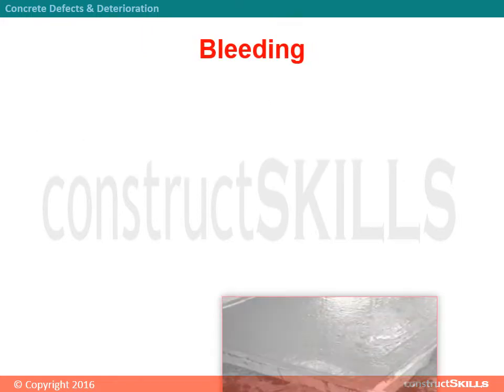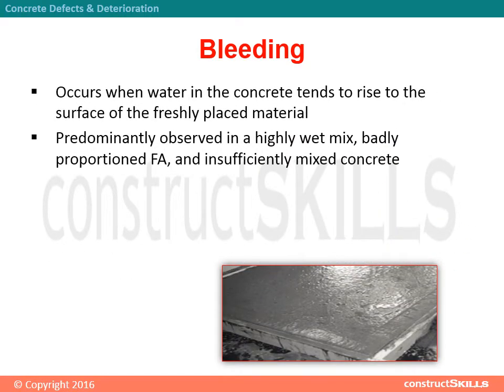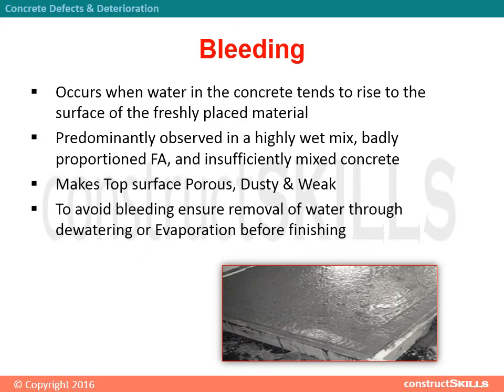Bleeding occurs when water in the concrete tends to rise to the surface of the freshly placed material. It is predominantly observed in a highly wet mix, badly proportioned fine aggregate, and insufficiently mixed concrete. Bleeding makes the top surface porous, dusty, and weak. To avoid bleeding, ensure removal of water through dewatering or evaporation before finishing.